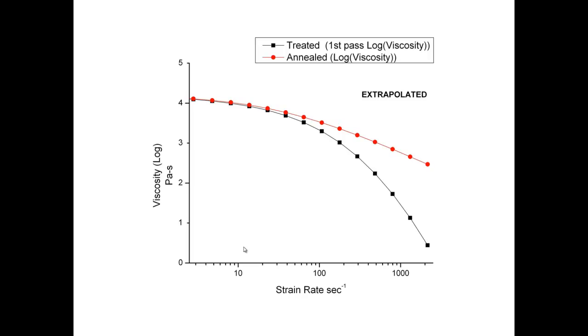So in an injection molding machine, for instance, you would benefit quite a bit from the black melt. Of course, this black melt, if you let it stay too long in your machine, will return to the red curve. This is what's happening here by doing two frequency sweeps, one after the other, and waiting a certain holding time at temperature. Actually, these curves are obtained at 225 for polycarbonate, and we go to 275 for 5 minutes, and we see that the melt is returning to the virgin curve.